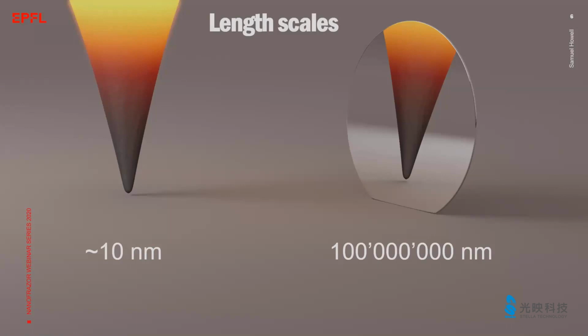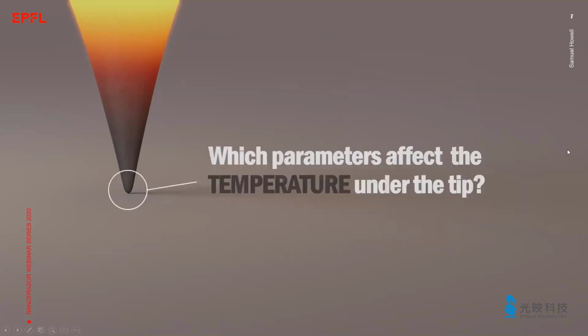But on the other hand, due to the large size of the substrate, it acts as a huge heat sink, and hence only the material directly in contact with the tip is heated. This is good news because a significant temperature increase is only achieved right under the tip apex and allows for creating structures at a very high resolution. Clearly, the temperature is an important parameter in TSPL as it defines whether patterning occurs or not. Hence, it's vital to understand which parameters affect the temperature.